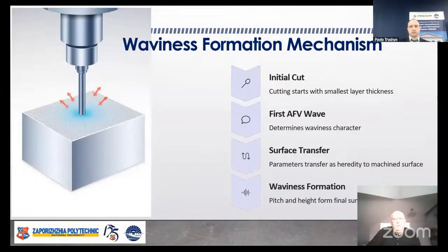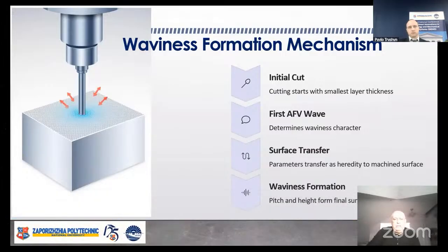All above allow us to formulate the waviness formation mechanism. The first, initial cut. Cutting starts with smallest layer thickness and does not depend upon the value of the feed rate. First AFV wave determines waviness character. Surface transfer. AFV parameters transfer as heredity to machine surface. Waviness formation. Pitch and height form final surface quality.